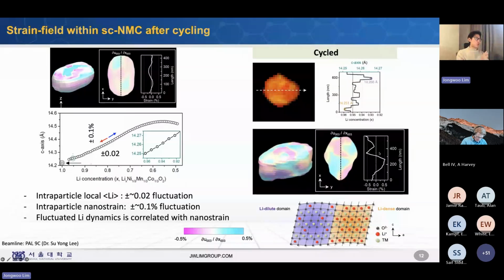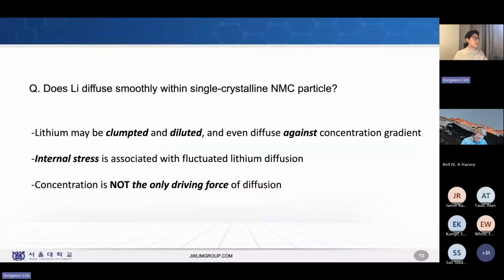So long story short, does the lithium diffuse smoothly within a single crystalline NMC particle, which is known to be a solid solution with the lithium? The answer is that lithium is often clumped and diluted, and can even diffuse against the concentration gradients. And those fluctuations in the lithium concentration gradient are associated with the internal stress. And now I want to highlight that diffusion is not only driven by the concentration gradient, but also strain, stress and many other factors.